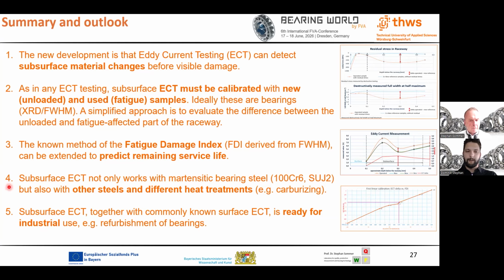The results also indicate that subsurface ECT is not only limited to standard martensitic bearing steel. Comparable trends are also visible for other steels and different heat treatments, such as carburizing. Finally, subsurface ECT together with the commonly known surface ECT is ready for industrial use, for example in bearing refurbishment.